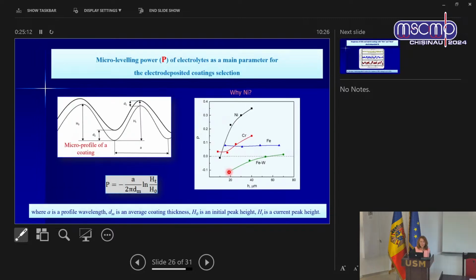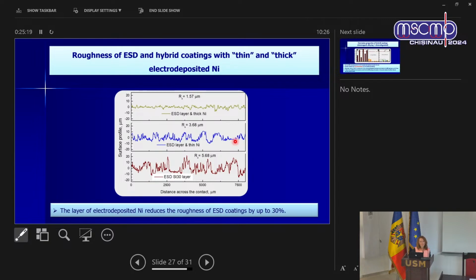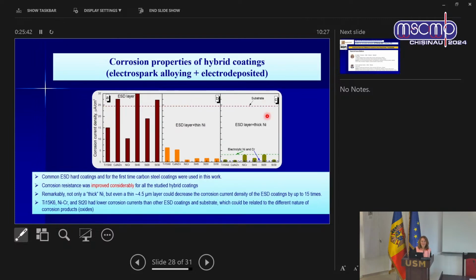as you can see here, for example, this is the initial roughness of electrospark coatings. After a thin layer of nickel, the roughness is already diminished, and if you grow even more, you diminish it even more, like 30%. So it was a good idea. Another good idea was for corrosion properties, because this thin layer, to be short, the smaller the box, the better. So the smaller boxes you have here, the better the corrosion resistance. So it's improving the properties of this material a lot. Like this, we were able to make a hybrid coating and have an innovative approach.